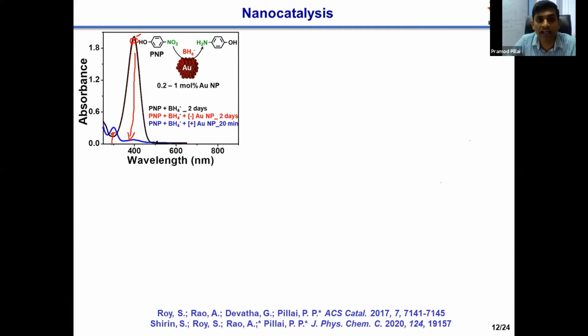And the important part here is that we don't see any characteristic absorption peak for nanoparticles. People who are working with gold nanoparticles know that gold nanoparticles have a strong absorption around 520 nanometers. Here you can see that there is no strong peak corresponding to the nanoparticle, which means that the amount of nanoparticle catalyst that we are using is very, very little.